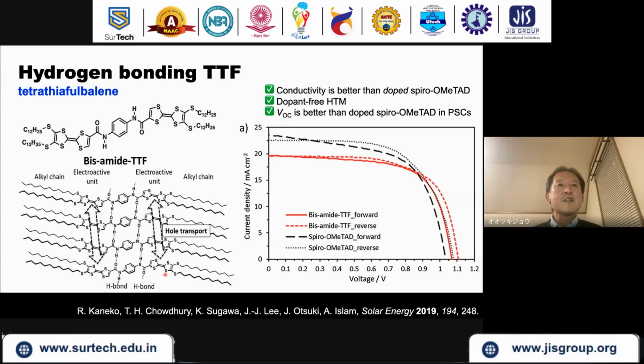And so we applied this material as a hole transport material in perovskite solar cells. And we found that the conductivity is better than doped spiro-OMeTAD, so we can avoid using dopant. The use of dopant has some disadvantages, like dopant is an ionic species, so it attracts water, humidity from the atmosphere, and that deteriorates the durability or lifetime of the solar cells. So we don't want to use dopant if possible. This is a very strong electron donor, so this material doesn't need dopant.